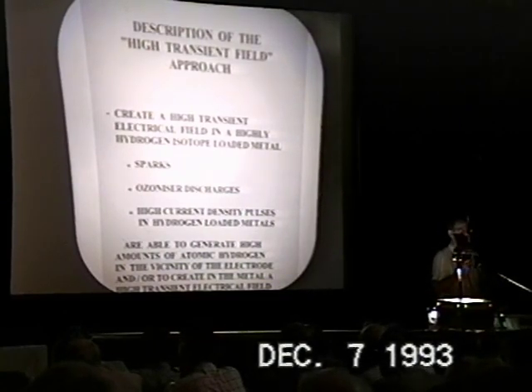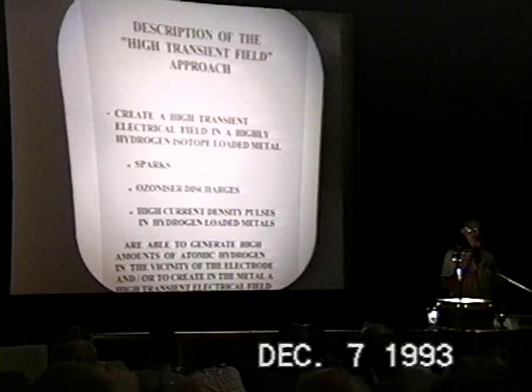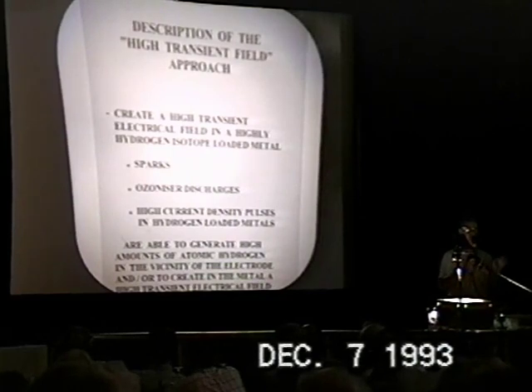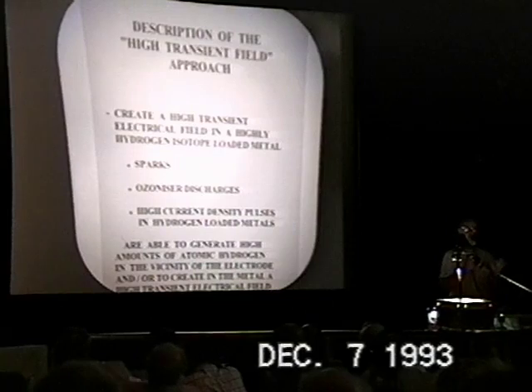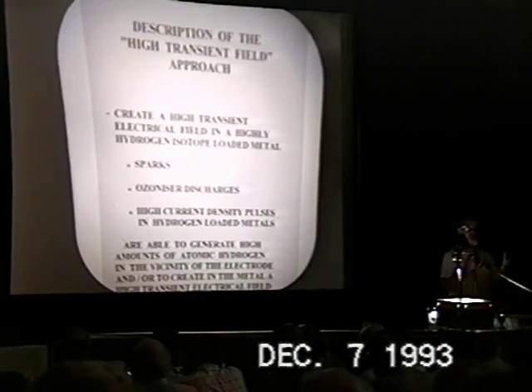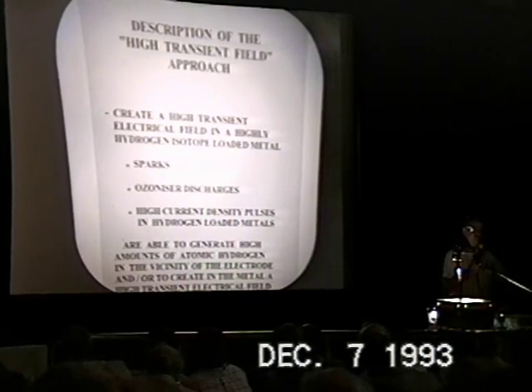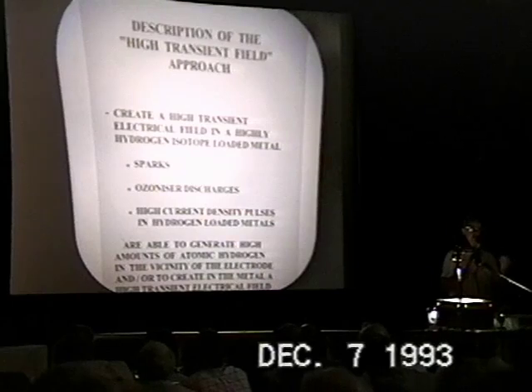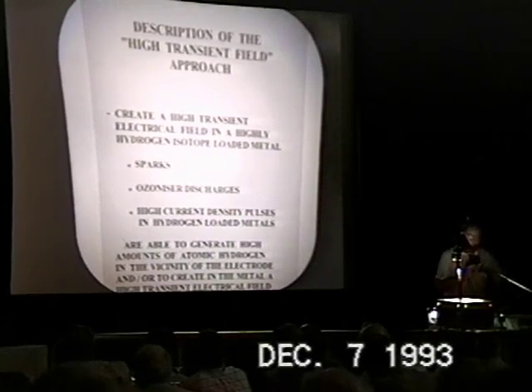The idea behind it was that when the spark is hitting an electrode, two things happen. The first is that you have a great amount of atomic hydrogen or deuterium generated, which can, of course, increase, as the impact, the concentration of hydrogen or deuterium in the palladium.